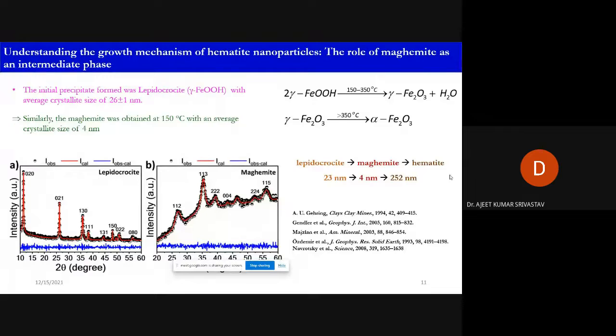But if you see in terms of sizes, lepidocrocite, what you start with, is 23 nanometers, and then 4 nanometers is the average size for maghemite, and then for hematite, suddenly you get 252 nanometers. So there is a huge difference between what you start with, what you have for the intermediate phase, and what you have for the hematite, the final phase. The point is here, one thing we have made clear, that the size is increasing enormously at this stage where maghemite is transforming to hematite, where the size is increasing from 4 nanometers to 250 nanometers. Fine.